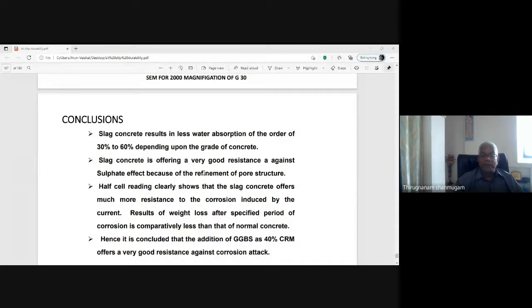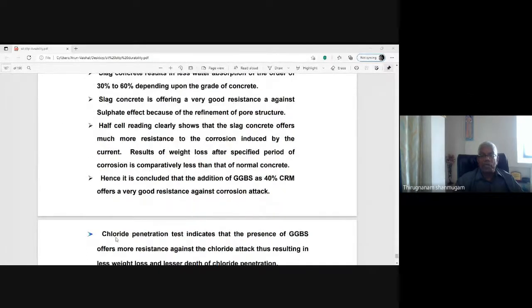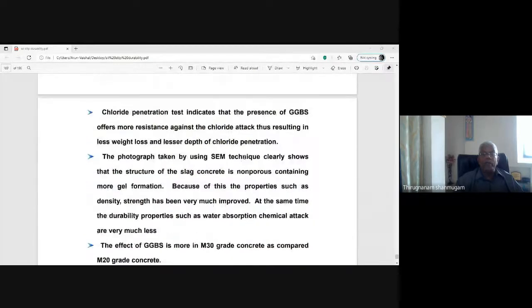because of the refinement of the pore structure. Half-cell reading clearly shows that the slag concrete offers much more resistance to the corrosion induced by the current. We conclude that the addition of GGBS as 40% CRM offers a very good resistance against corrosion attack. The chloride penetration test indicates the presence of GGBS offers more resistance against the chloride attack, thus resulting in less weight loss.